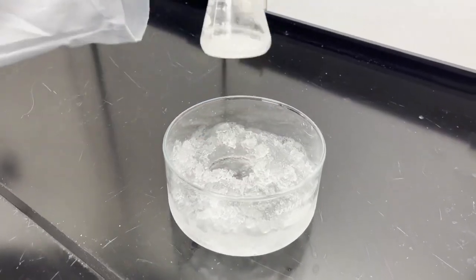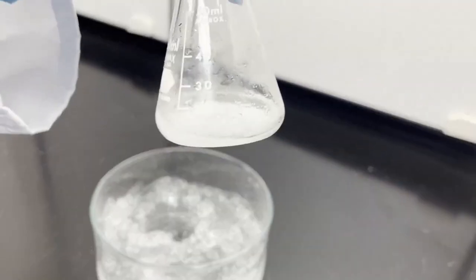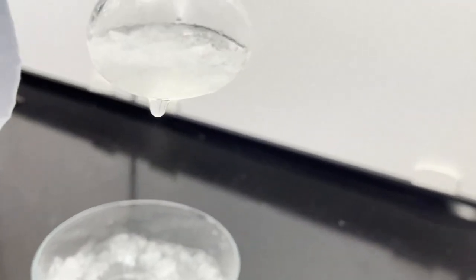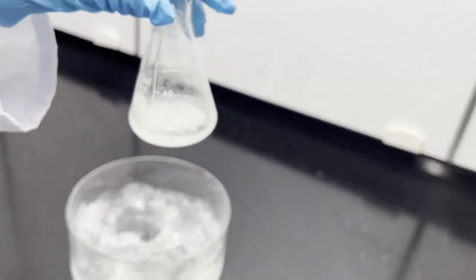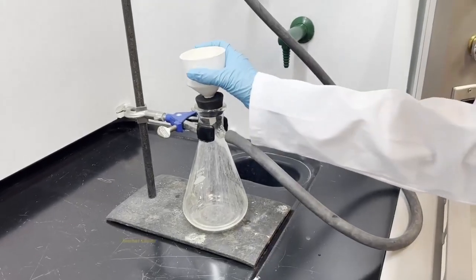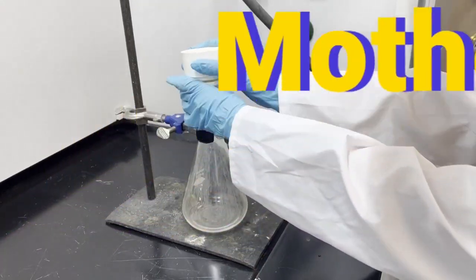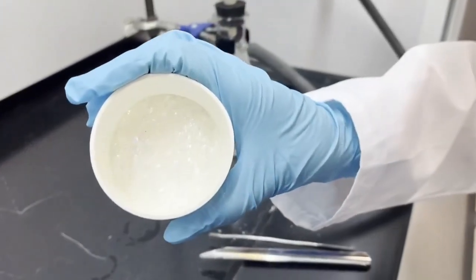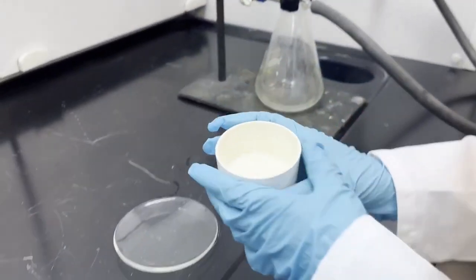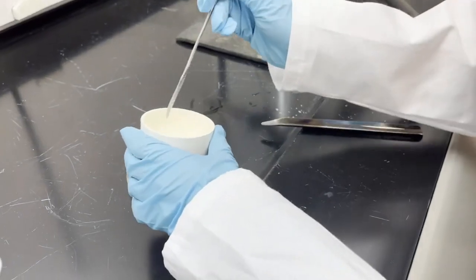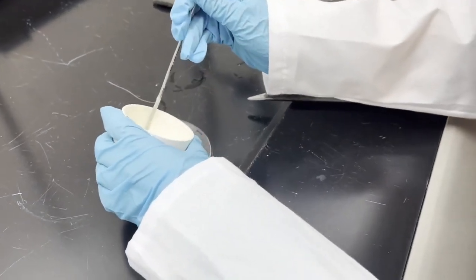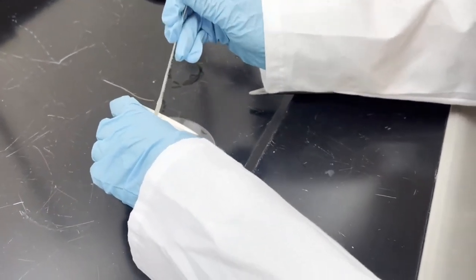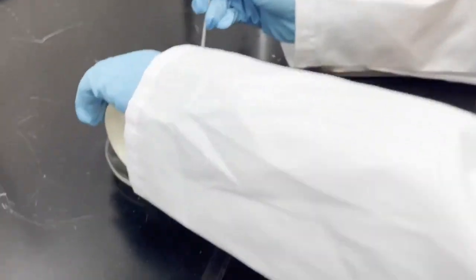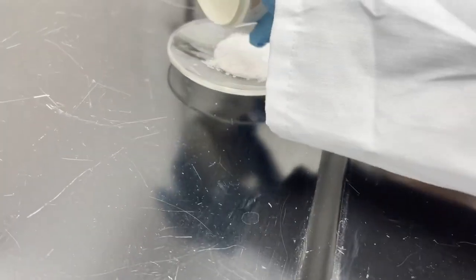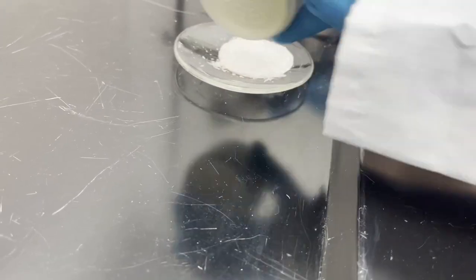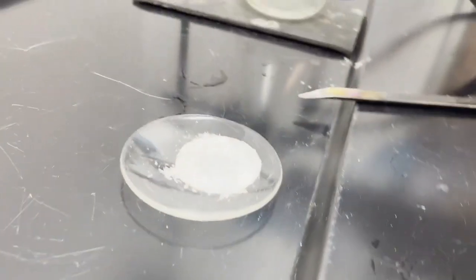When you start to notice that there are no more crystals forming in your solution, the crystals can be separated from the solution via vacuum filtration. The solution can also be referred to as the mother liquor. Use some of your chilled solvent to wash the mother liquor off of the crystals, then place your compound on a weighed watch glass. Don't forget to remove the boiling stones, and let your compound dry for at least 24 hours before weighing it. Now you know how to recrystallize from a known and an unknown solvent. Good luck recrystallizing your compounds!